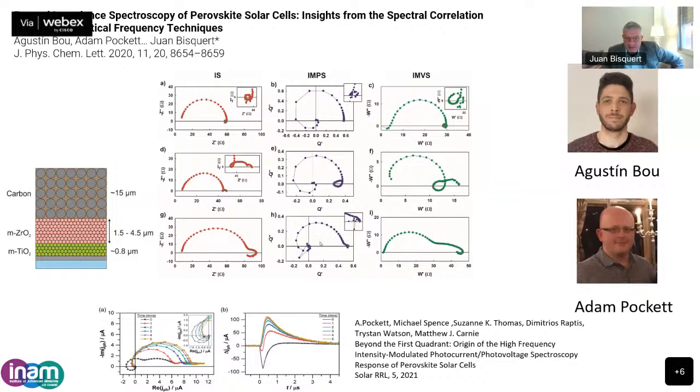So these measurements are very reliable. It's a very large negative part. As I said before, we did suppress this part because we didn't understand it at the time of publication, but it's giving a negative part, and this part contains information now about the diffusion coefficient of the perovskite solar cell, while the impedance spectroscopy doesn't have it.